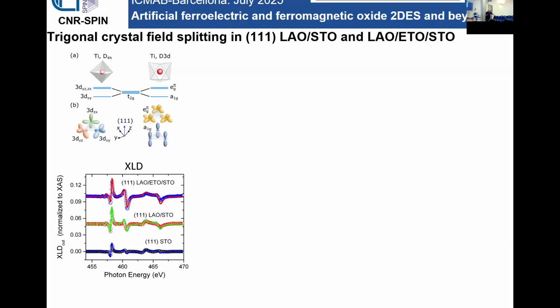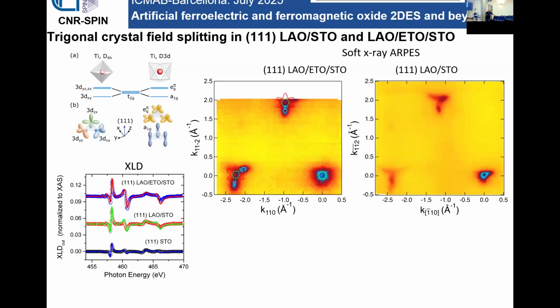So I think it's very complicated, because this morning I read again the quantum metric paper from Caviglia. And at the end, most of the effect they see, as written in the paper, they see when they cross the second band pairs, even in a picture where there is a trigonal crystal field splitting, because they put in a trigonal crystal field splitting. So I think it's complicated, this story.